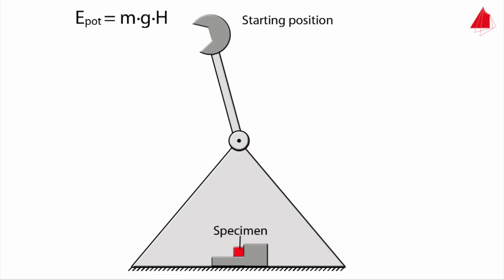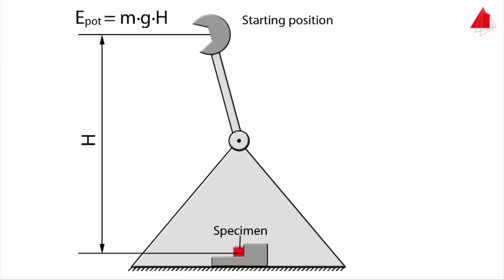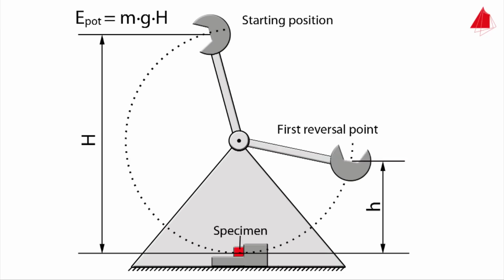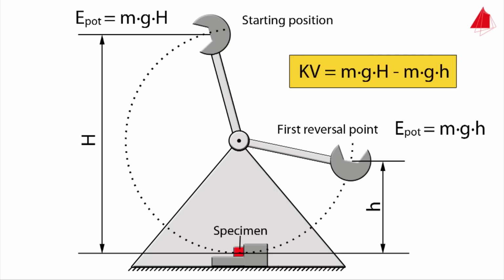Here is the main principle of the measurement. In its starting position, the pendulum only has potential energy. It is given by mass of the hammer m times gravitational acceleration g times starting height capital H. After the pendulum has been released, the hammer moves downwards, hits the specimen and then only swings to height small h. Exactly at the first reversal point, the pendulum again only has potential energy, which is m times g times small h. The energy that has been absorbed by the specimen is called notch impact energy, KV. It corresponds to the difference between the two potential energies.